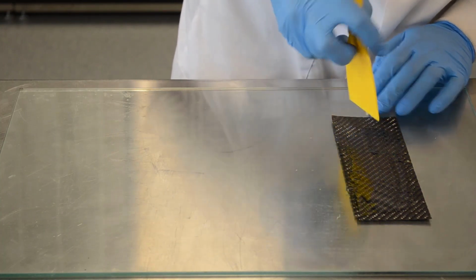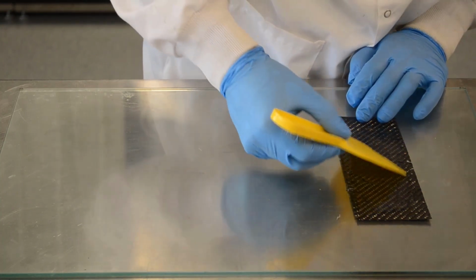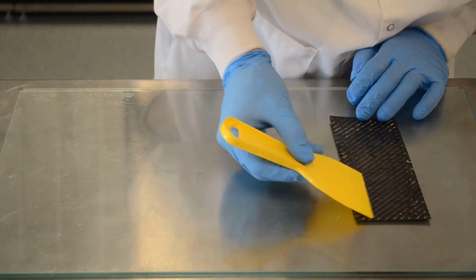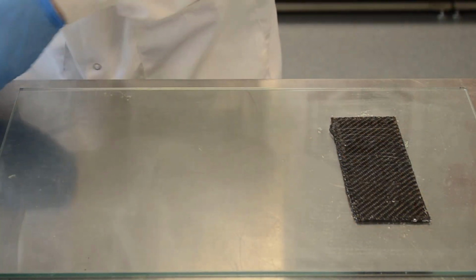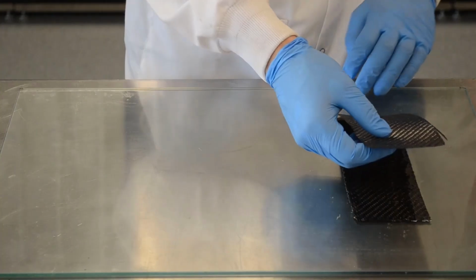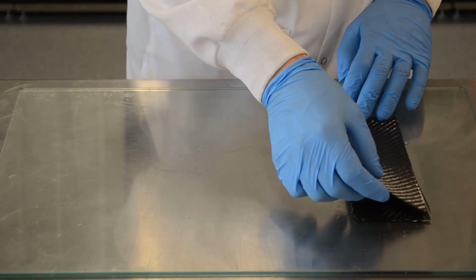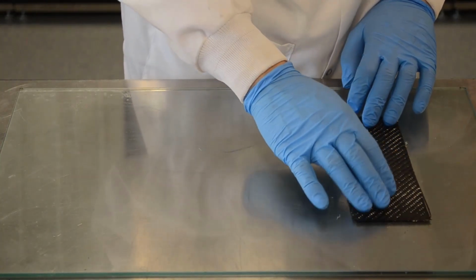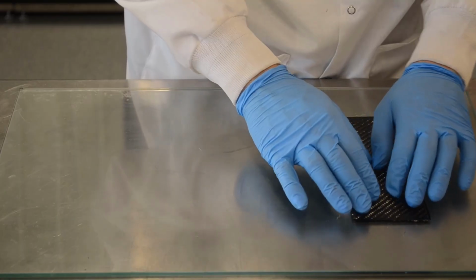Avoid placing excessive resin into the laminate as it can lower the fiber volume fraction and waste additional resin, although excess resin will mostly be removed from the part by vacuum consumables if they are used. While placing the plies and spreading resin, avoid deforming the fabric. Wavy fibers can reduce mechanical properties and affect the appearance of the part.